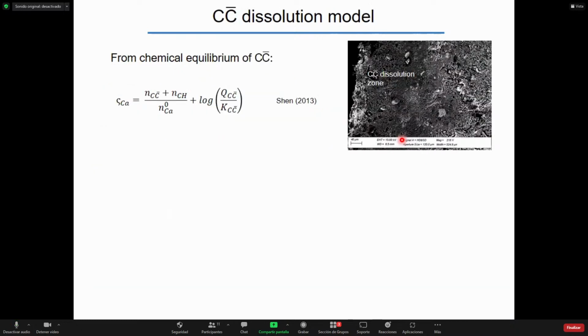For this, we use Shen's model, which simplifies the chemical equilibrium of calcite into one single variable called sigma. This variable sigma depends on the moles of calcite and portlandite, on the equilibrium constant of calcite, and its ion activity.